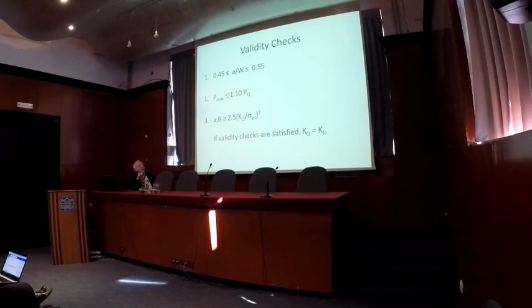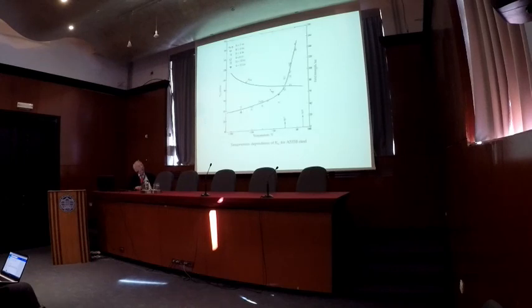Now, KQ is the K that's calculated from the PQ, and it's called a provisional or tentative value of K1C. If you meet all these validity checks, then you call your KQ K1C, and you have successfully done that K1C test. Here are some data.